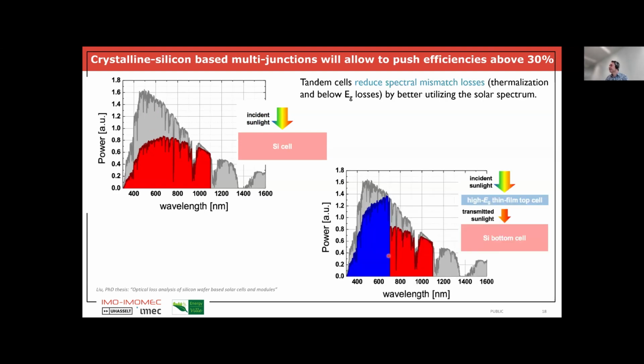But if we go to a tandem device, which means we take the silicon as a bottom cell and we put a high bandgap material on top, so a second solar cell on top, then we can actually make better use of the spectrum of the incoming light. And part of the photons, the high energy photons, the blue part here, will be absorbed and converted by the top cell. And you see that because the band gap is higher, we can use more of the incoming energy of those photons. We have less gray area here, less losses. And then all the light that is not absorbed by the top cell will be absorbed in the bottom cell.